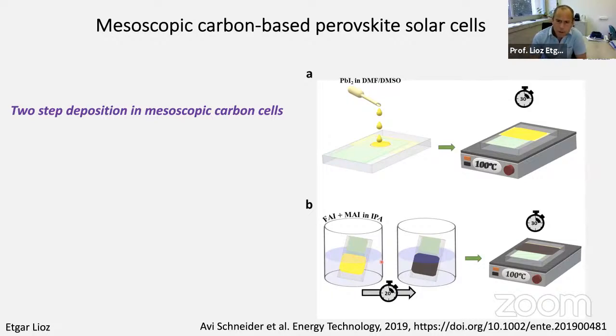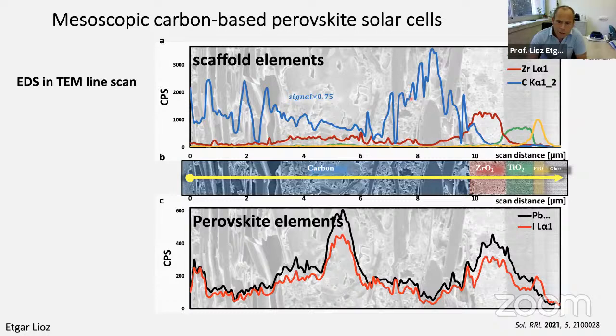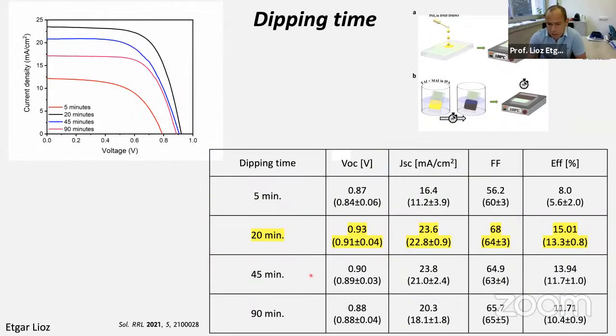As you can see here, we did some EDS line scan after FIB cross-section in order to see that all elements penetrate the whole way, because we are talking about 10 to 11 micron devices. It is not obvious that everything is penetrating. This proves that the penetration is really essential for the performance of the cell. We did the optimization of the dipping time in order to get the best performance. We achieved about 15% efficiency. This is quite high for those kinds of cells, one of the best today.